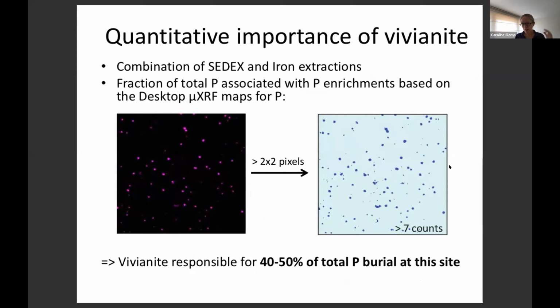One is we combined our phosphorus extractions with iron extractions and did all sorts of calculations with typical ratios of iron to phosphorus. And then we could calculate that roughly 40 to 50% of this fraction was Vivianite. We also used our direct measurements from the micro-XRF and estimated the size of these pixels and assumed that the count intensity there told us something about the concentration. And these rough calculations actually gave the same number. About 46% of this phosphorus was Vivianite.